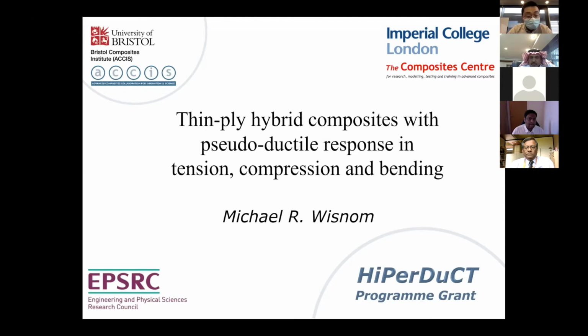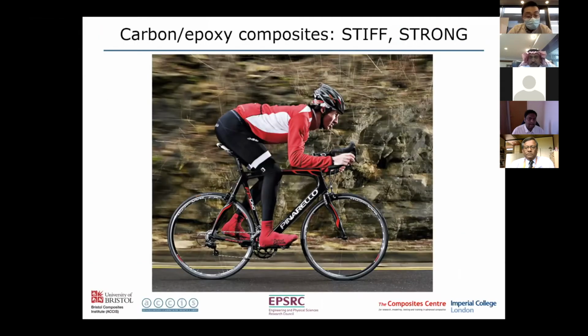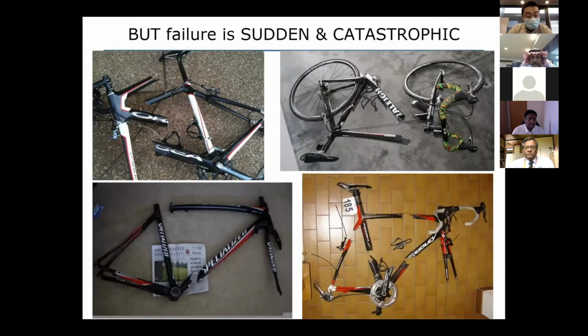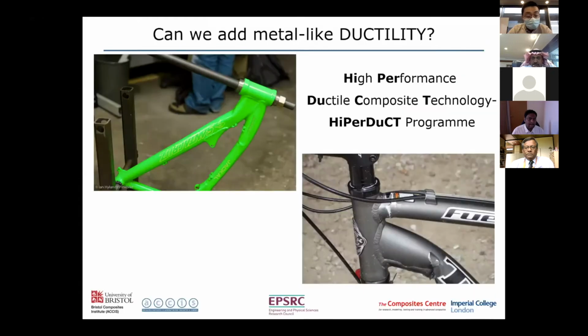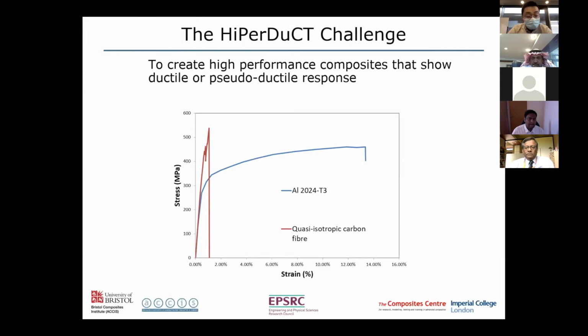So carbon fiber composites are great materials. They're stiff, they're strong, they're light, they're durable, they lack corrosion problems, but they do have a problem. When they do fail, it tends to be a sudden and catastrophic failure, and that's a really undesirable aspect of the composites. So the question arises, can we add metal-like ductility? So we keep the benefits of the high-performance composites, but actually introduce a more gradual failure. So that was the challenge in this program, the HyperDuct program, where we wanted to create materials which show the great response of composites, but have some sort of ductile or pseudo-ductile response.